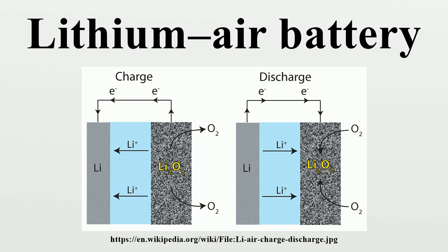Cathode and electrolyte. At the cathode during discharge, oxygen accepts electrons via reduction. Mesoporous carbon has been used as a cathode substrate with metal catalysts that enhance reduction kinetics and increase the cathode-specific capacity. Manganese, cobalt, ruthenium, platinum, silver, or a mixture of cobalt and manganese are under consideration as metal catalysts. Under some circumstances, manganese-catalyzed cathodes performed best, with a specific capacity of 3137 mAh per gram. Carbon and cobalt-catalyzed cathodes performed second best, with a specific capacity of 2414 mAh per gram.